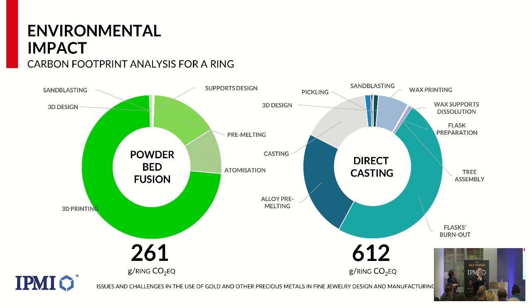You have to consider that for every 200 to 300 grams of cast part in jewelry, you have 2 kilos of investment. So once you have made that investment, you need to treat it or do something with it. And it was not considered. This was only the energy needed for making the entire process. But it's quite intuitive. A single phase process needs much less energy than a process with many phases, compared to casting, where every single phase has a yield and you misuse energy in every single one.